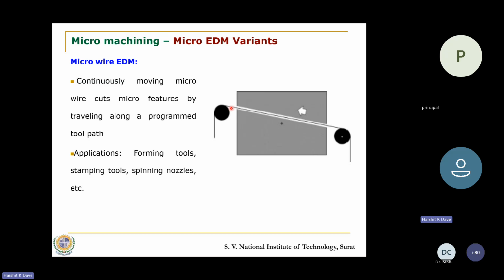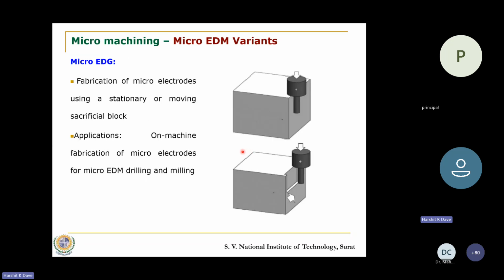Rather than cutting say 10-15 mm of length, we may cut 1 or 2 mm of length and create a feature by cutting that small size. So certain forming tools or stamping tools or spinning nozzles are made by the micro wire EDM process. A small variation is micro electro discharge grinding.